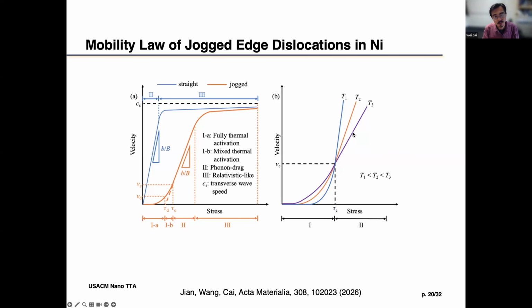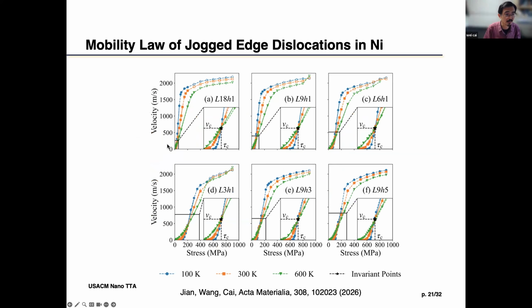Above the critical point, it's in the phonon drag regime, so increasing temperature will decrease the velocity. And right at the invariant point, it actually does not change. So this is a schematic. I'll show you the data. The data looks like this, but if you zoom in, they all seem to nicely cross an invariant point.